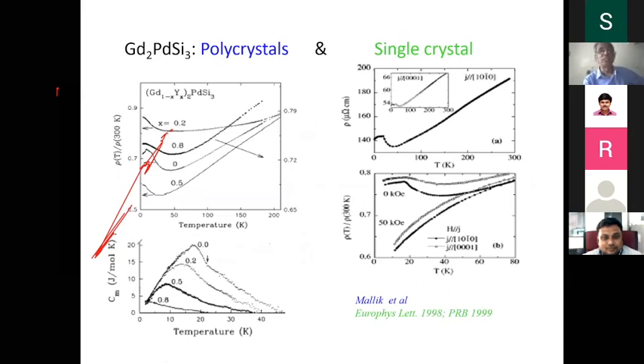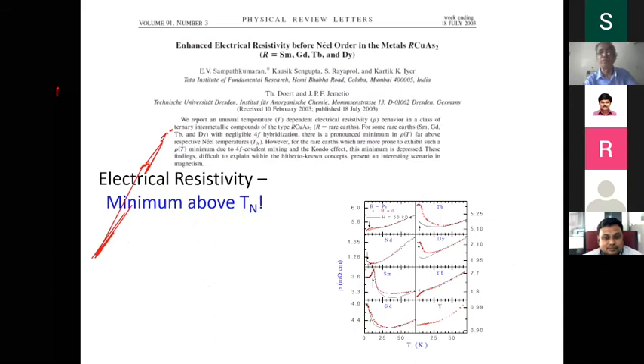This was not understood. We have found and reported half a dozen such materials. We have papers also in PRL to show that even in such a normal system, where you don't expect any 4f delocalization, the experimental data shows as if it is delocalized, as if it is Kondo, but it is not coming from the Kondo effect. This concept was not completely understood till recently. There is a paper in PRL. Okay, there are other materials for which we have papers in PRL. If you look at samarium and gadolinium compounds, there is also a minimum here, then an upturn before the magnetic order.